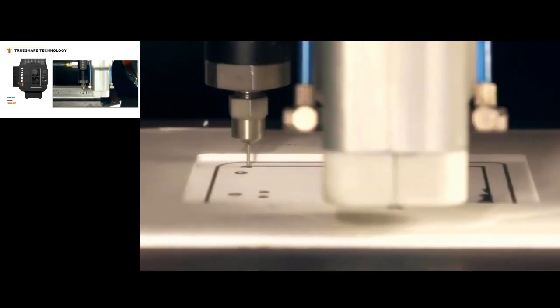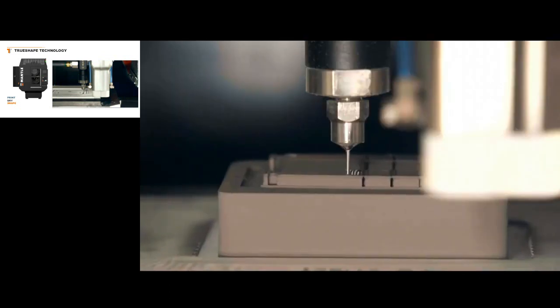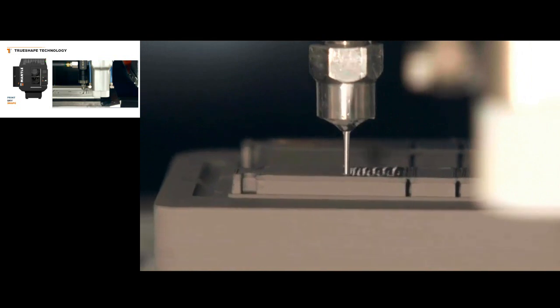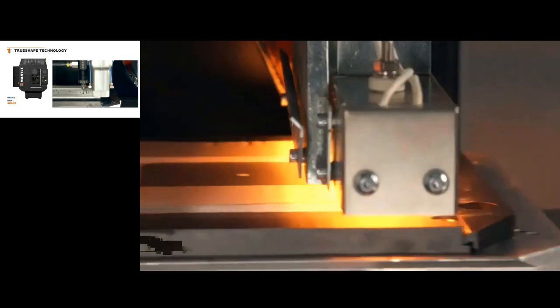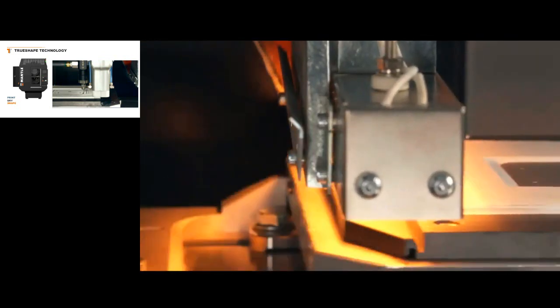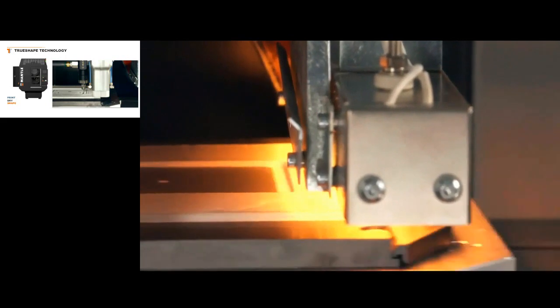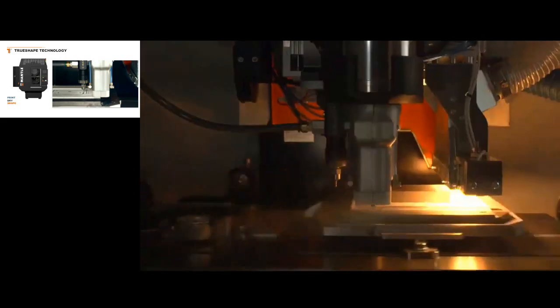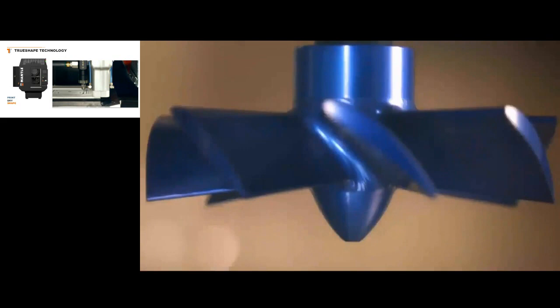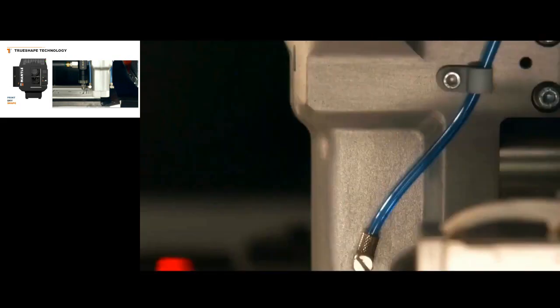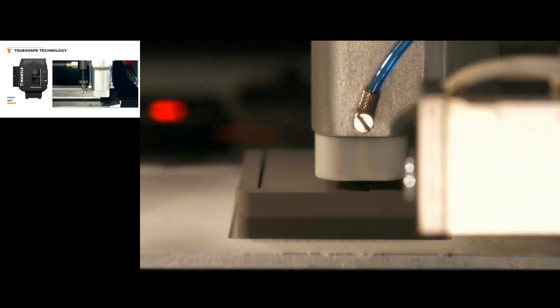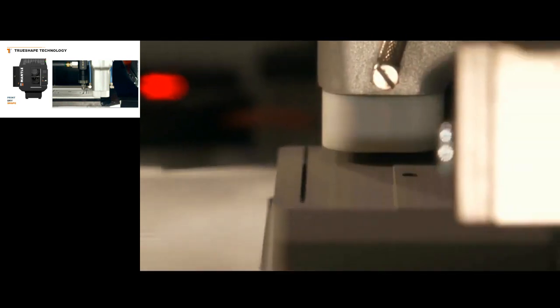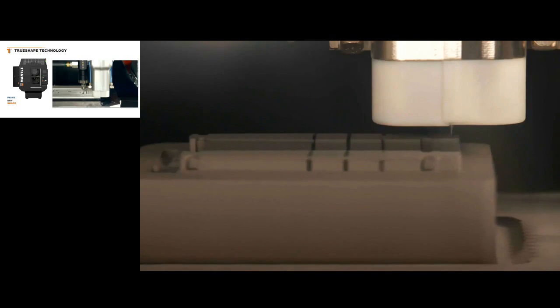So we extrude the material, we're printing here, and we build up layer by layer. But after each layer, we heat and we dry, and that removes the liquid. And so we're removing the liquid and converting what was a paste into something that's like a foam that can be machined very easily. And the machining generally takes place in a couple operations. One is after every layer, we'll do a very quick facing operation to remove a small amount of material and make it perfectly flat before the next layer.